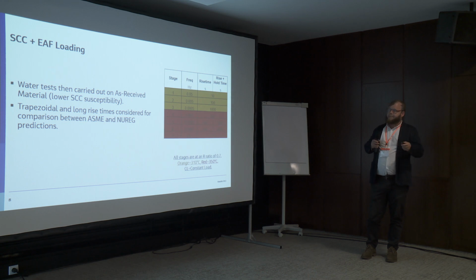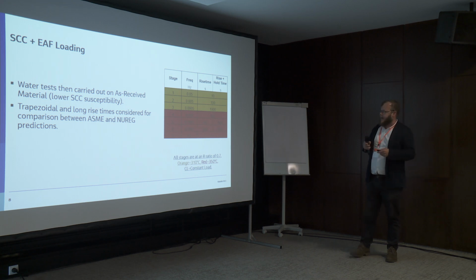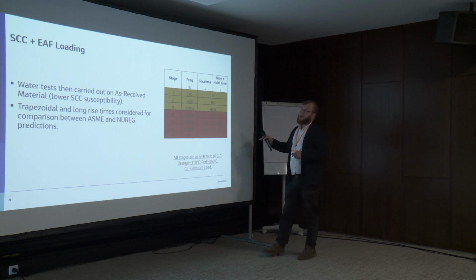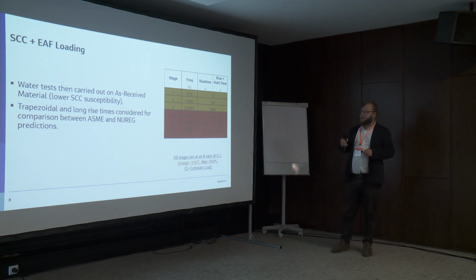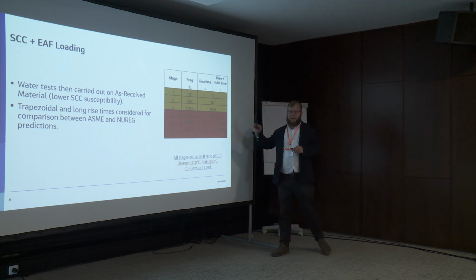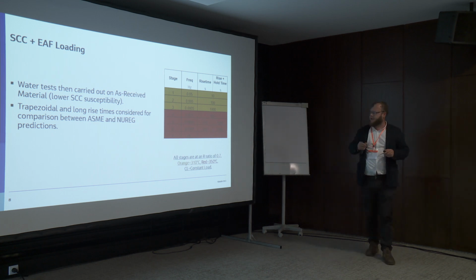So after carrying out these baseline fatigue tests, we've then carried out the combined SCC and fatigue test, where we've included the rise time. So that's in these two stages. It's pretty difficult to see, but we've got 500-second rise and then a 1,000-second hold, and then a 500-second rise and a 9,000-second hold. The idea of these stages is not only to investigate the effects of the hold time in the fatigue loading, but also it allows us to transition to a fully engaged SCC crack before carrying out our final constant load stage where we can get our SCC crack growth rate.